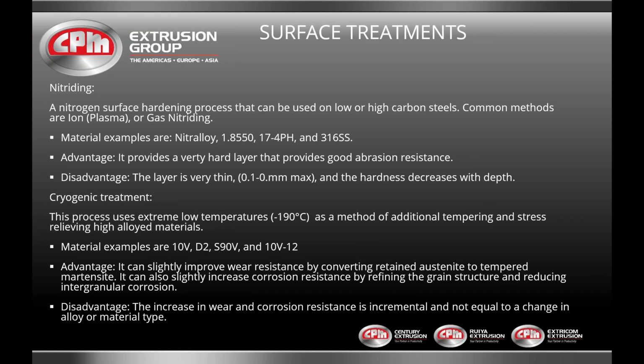Surface treatments include nitriding, a nitrogen surface hardening process that can be used on low or high carbon steels. Common methods are ion or plasma nitriding, or gas nitriding. Material examples are Nitralloy, the 1.855, etc. The advantage is it provides a very hard layer with good abrasion resistance. The disadvantage is that the layer is very thin.